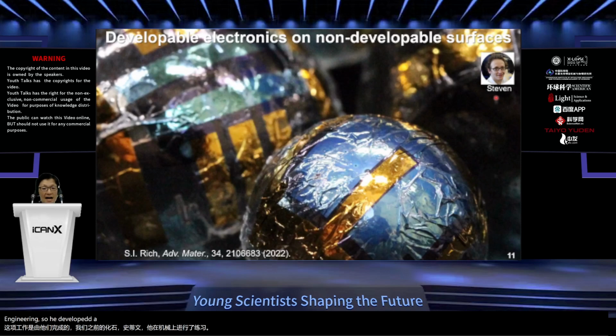So he developed a very nice approach using a lamination process with thermally shrinkable films. He combined the thermally shrinkable films and our very thin organic solar cells or organic devices. And he attached such shrink film and ultra-thin devices onto curved surfaces like a sphere, as shown here. And he applied heating, 130 degrees C, to the whole system. Then the devices automatically shrunk and conformed to any complex shape of the curved surfaces, as shown here. So even after such a process, the organic solar cell worked perfectly because our organic solar cells have both good mechanical robustness and very good thermal stability.